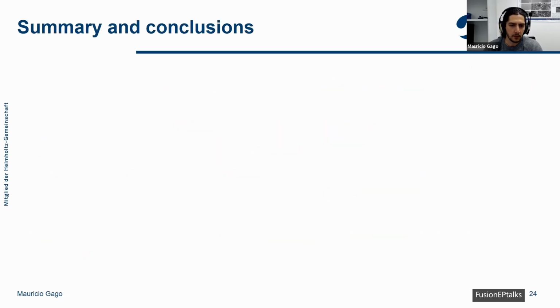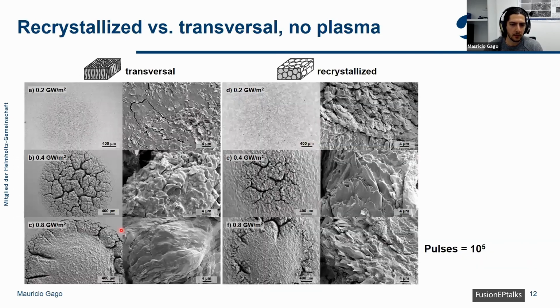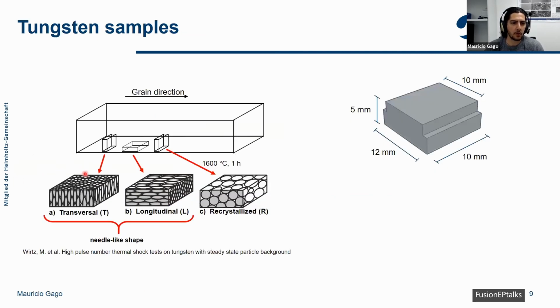Yeah, so the reason why the transversal crystal structure is preferred is because if we have the longitudinal crystals, so I can maybe go back quickly. Here. So when a crack forms here, it goes basically perpendicular to the surface, right? And if we have a longitudinal microstructure, when a crack forms, it can form here, for example, and then it goes in this direction. And this forms a thermal barrier that makes it harder for heat to dissipate. And this is why it's not really preferred. And then also it can break off more easily inside the divertor. So these are the reasons why the longitudinal is not preferred. I don't know if that's clear, or if you have another question about this.